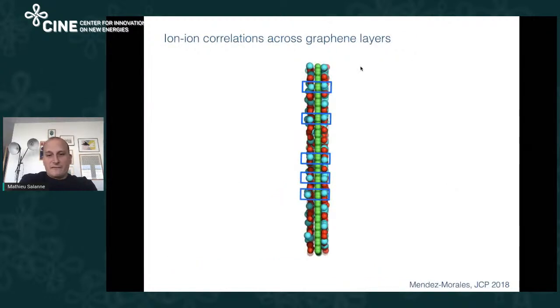Then an interesting effect that appeared when we looked at this graphene was that we observed a very particular arrangement. And this is something that was a bit surprising. So when you have this graphene structure, you see that ions of the same sign go in front of each other. And again, this is not so intuitive at first sight because in general, they would like to repel each other.